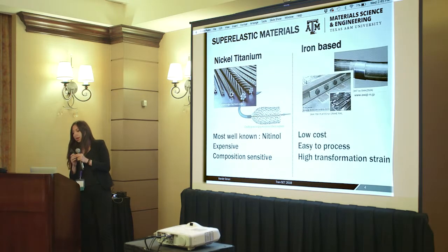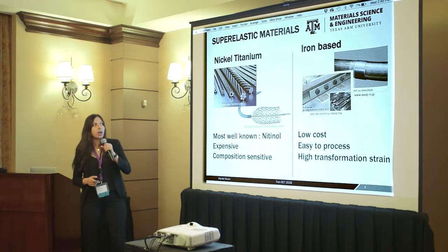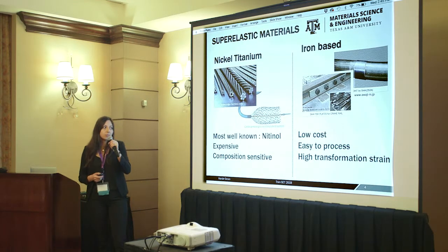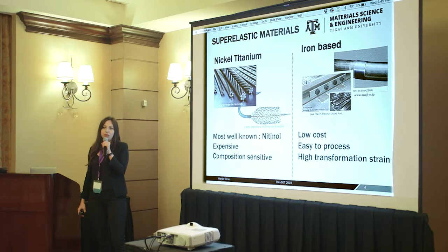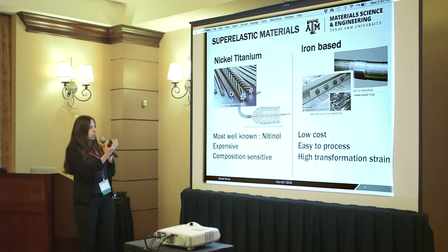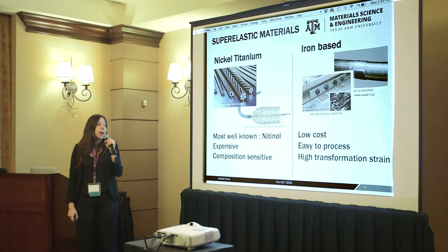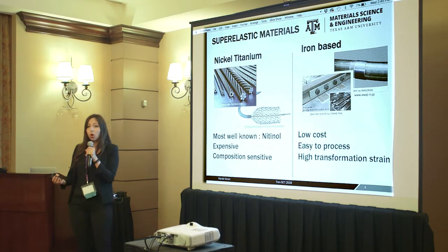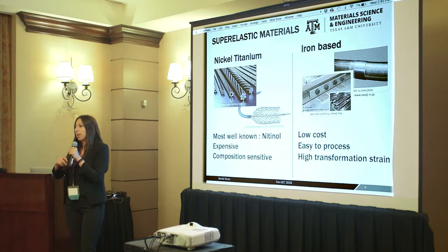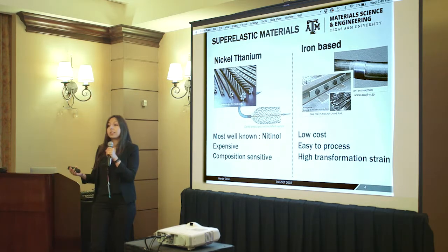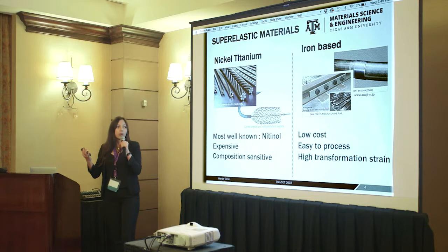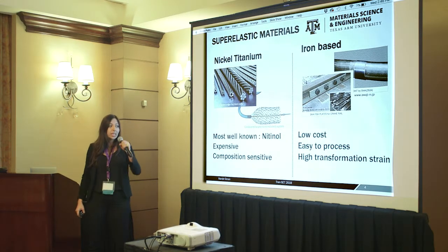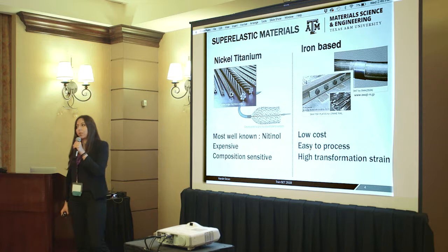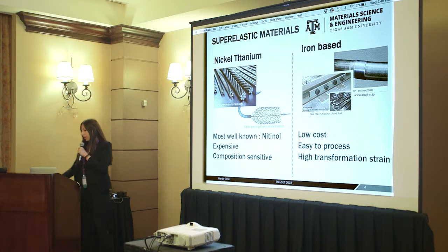However, iron-based shape memory alloys are much, much lower cost. That's why they are very suitable for civil engineering applications. They are very easy to process, so industry knows how to deal with them. You can do cold work up to 98%. And they can provide theoretically higher transformation strain than nickel titanium alloys.